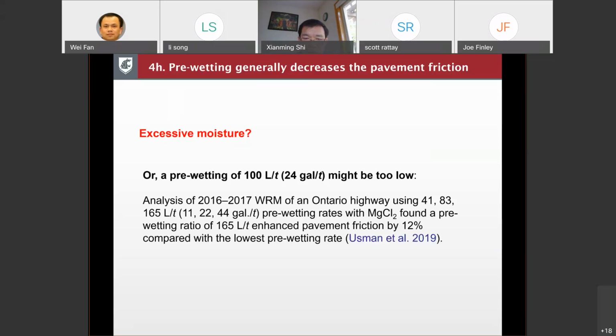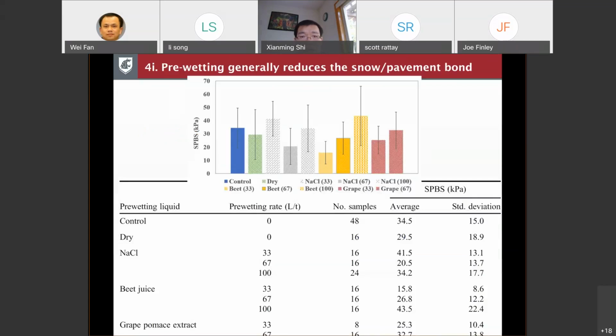The field study in Ontario is suggesting 44 gallons per ton as a better pre-wet rate. The caveat of the lab test is that, again, we didn't have a sufficient amount of traffic, even though 500 passes wouldn't probably be sufficient. And more importantly, the speed of the traffic is not as high. In the field, you are dealing with higher speed, so it will agitate the pre-wet salt into the ice layer much quicker and much more thoroughly. So that's the inherent limitation of the lab test.